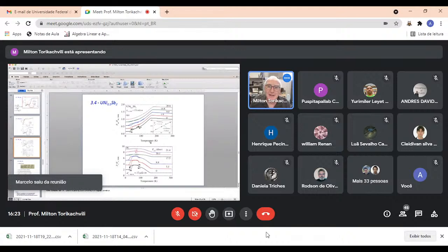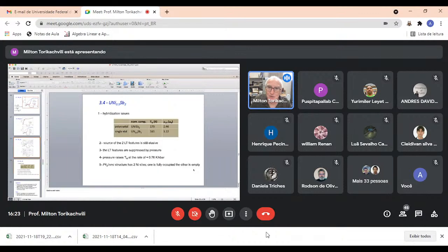Over here at the top panel, we have the resistivity normalized to 300 Kelvin versus temperature. These plots are shifted for clarity. So you see that at zero pressure, ambient pressure, you can see the features here at 40 and 80 in the resistance. But as you apply pressure, those features disappear. And that's true both when you are measuring along the plane or perpendicular to the plane. Very, very puzzling. So this is a problem that we still want to pursue.